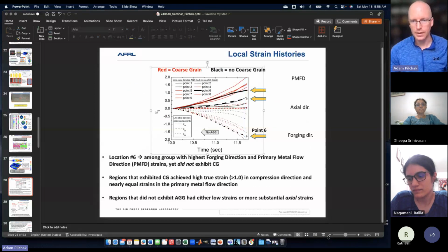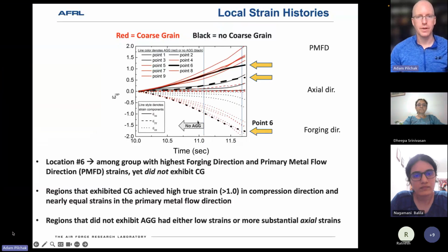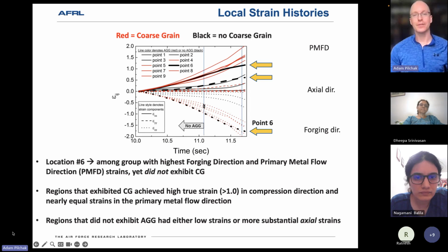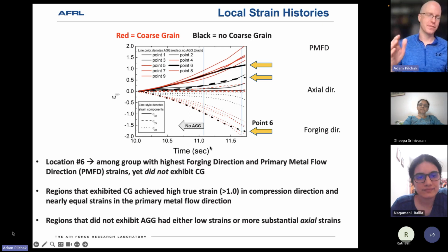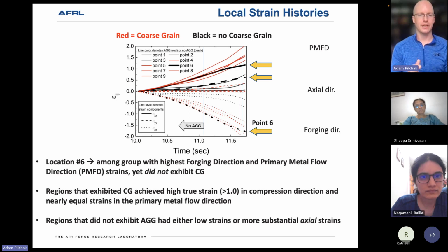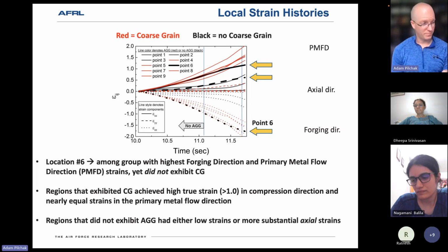So this was the critical plot here that I didn't really mention. This vertical line here, and it's funny that it's as a function of forging time, but it's ultimately tied to strain. So no abnormal grain growth was observed for locations that experienced a true strain less than 1, regardless of path. It doesn't matter how it was put in. So true strain of 1 does seem to be a critical condition. Our smallest reduction was like 56%, or maybe 60%, something like that, and we never saw it in that sample.